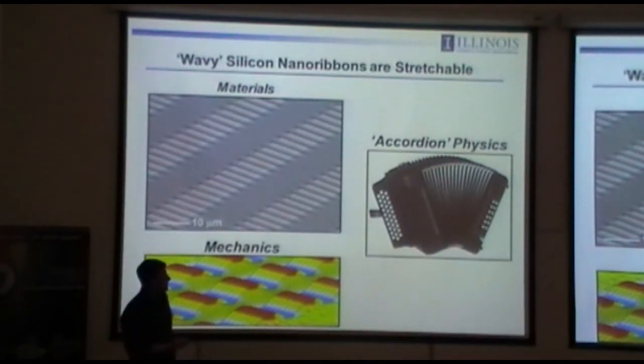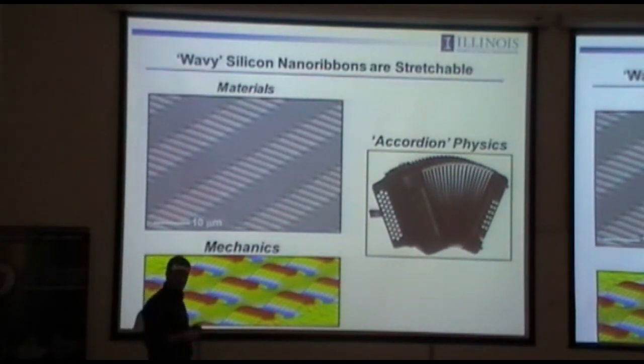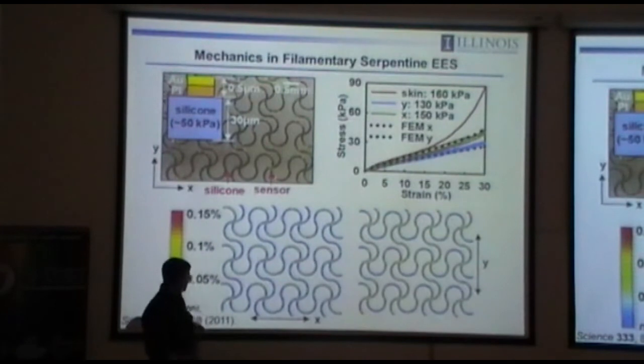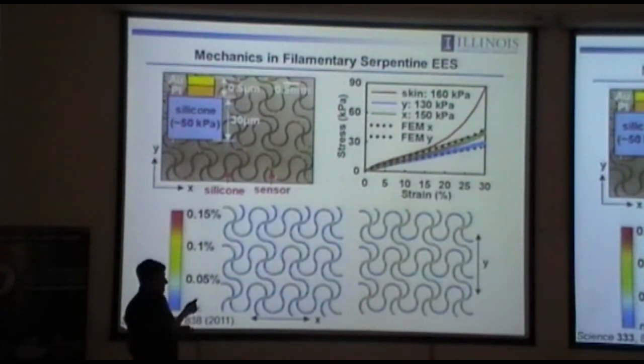But the mechanics turns out to be very subtle. You have very hard material and very soft material. They're intimately coupled by the surface chemistry. And it's a composite system at some level. And we spent nearly a year just studying the mechanics of this test structure because in these kinds of systems, mechanics design becomes as important as circuit design. You have to design the layout of the system so you can accommodate the maximum stretch defined by the application that you have in mind. So we've written probably half a dozen papers just on the mechanics of this system. But I won't go into the details of those aspects today. There's more details. So those are the ideas. Thin geometries to induce flexibility, and then controlled buckling mechanics to affect stretchability.